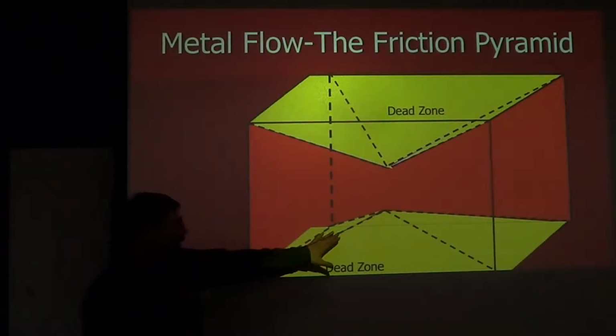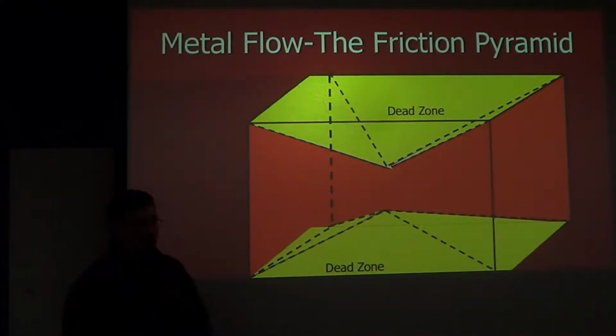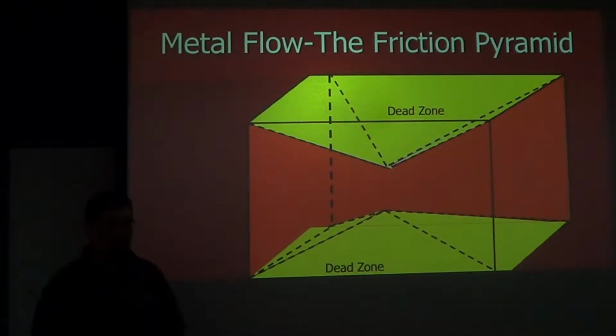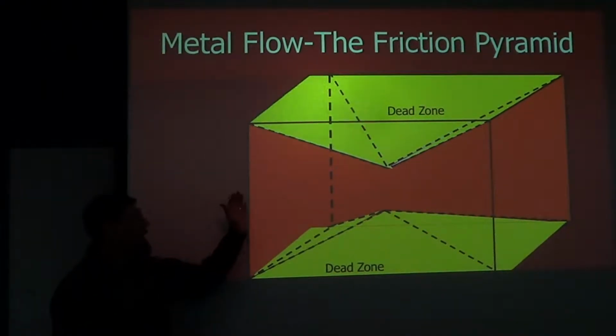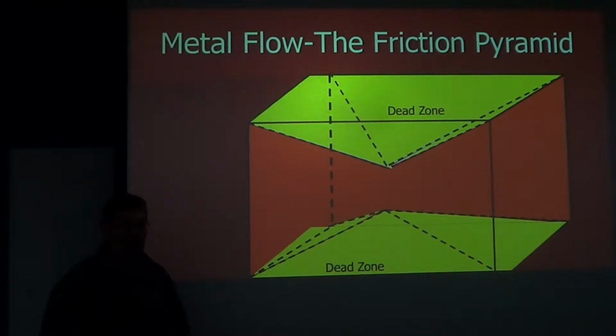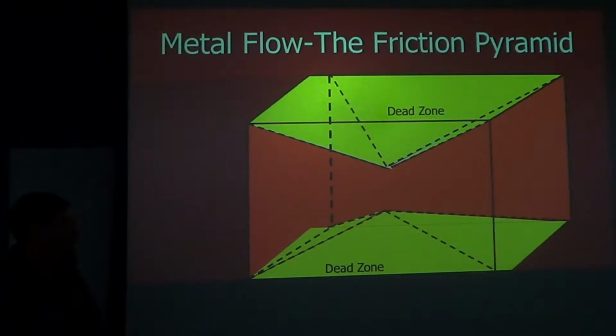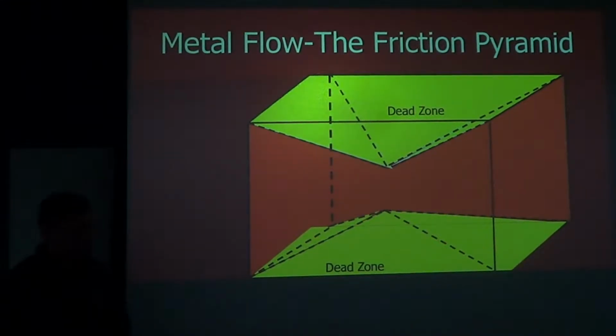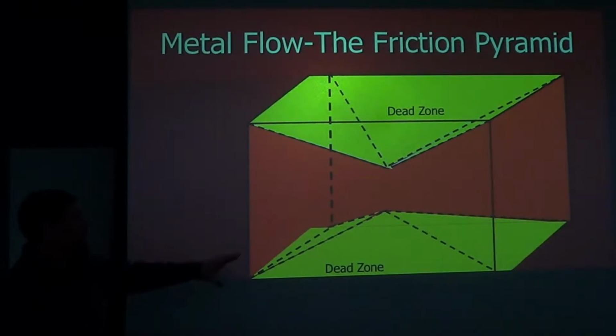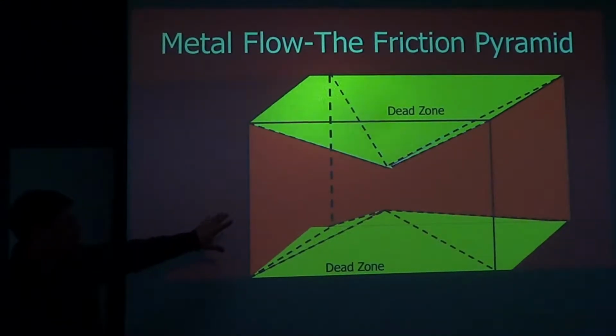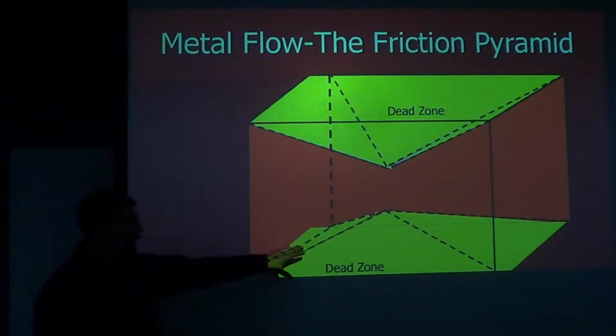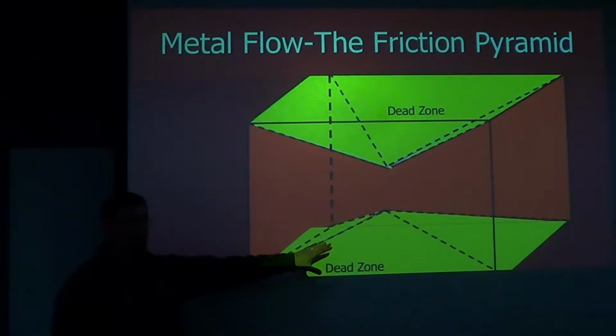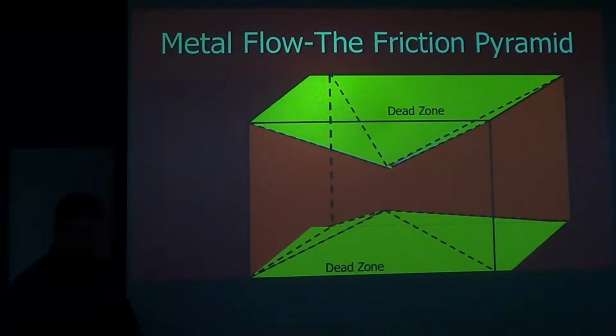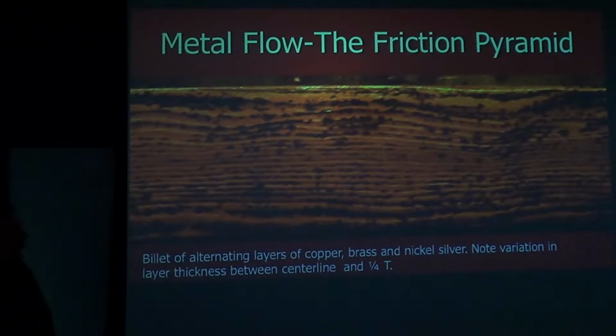So all this area in yellow is the material, the volume that's affected by the friction between the workpiece and the dies. And this area in red is that which is not affected by friction. So when we forge, the metal that's not affected by friction is free to move, where this is trapped, at least for a period of time it's trapped. I'll show that with some laminated material.